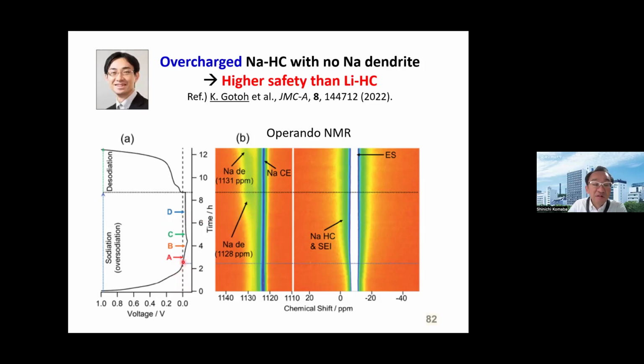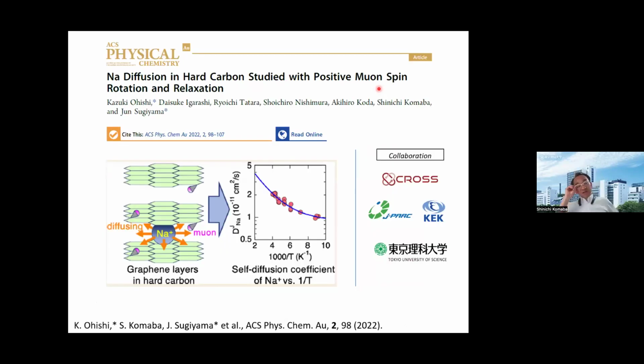And even in the case of overcharging by applying a potential lower than zero versus the sodium standard potential, because of the buffering effect of the sodium deposition, there is no dendrite formation. This means that higher safety than lithium can be achieved for the hard carbon electrode in a sodium-ion cell. And recently, we are also studying sodium diffusivity in the hard carbon, and we applied positive muon spin rotation and relaxation to analyze the sodium diffusivity in hard carbon.